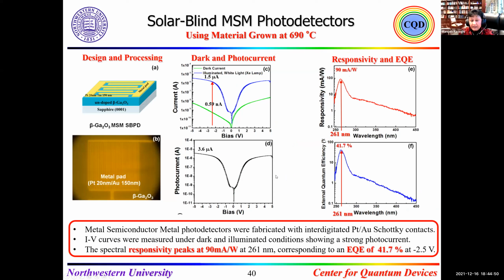And then we immediately did the MSM, because that's the easiest way to understand the cutoff and the energy gap. We saw it's 261 nanometers, and the external quantum efficiency is 41.7% at minus 2.5 volts. We did this many times, and that was the result we got.